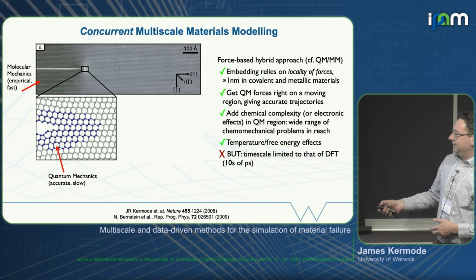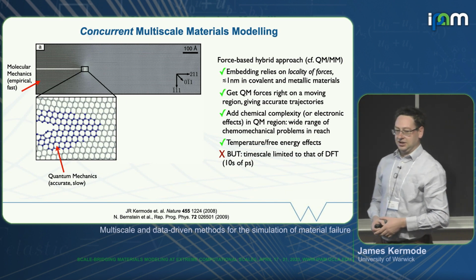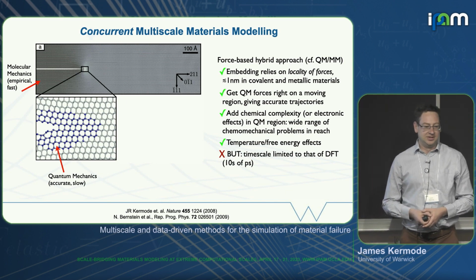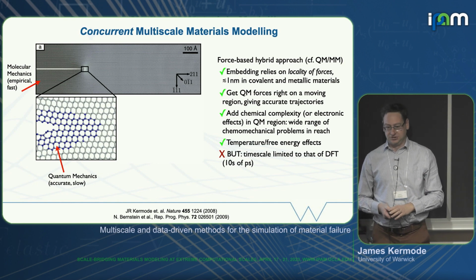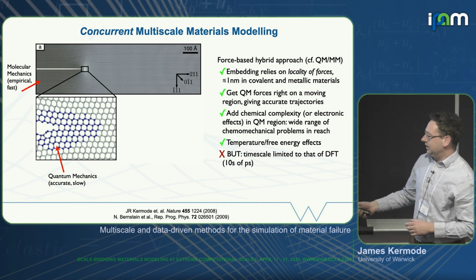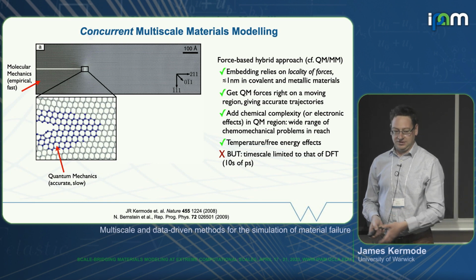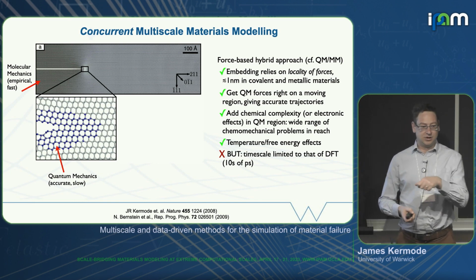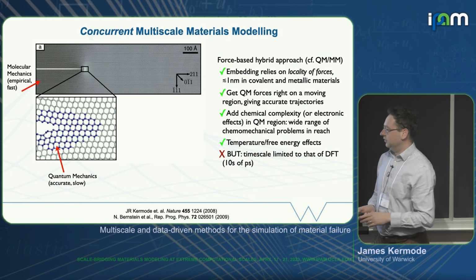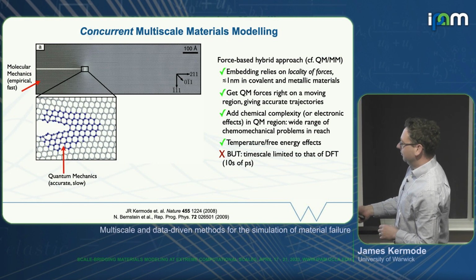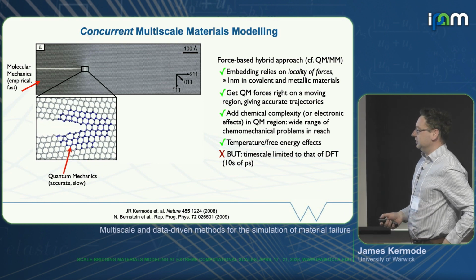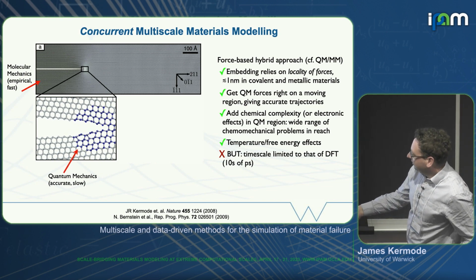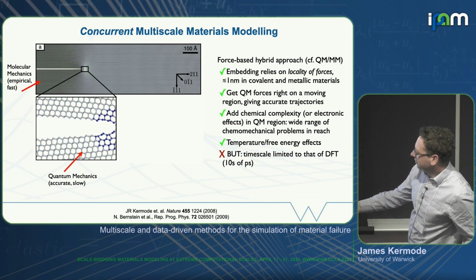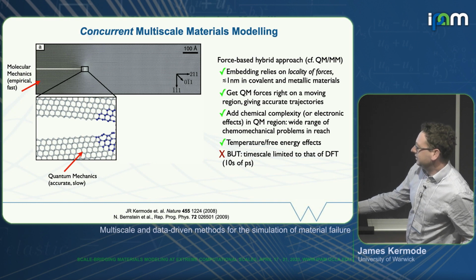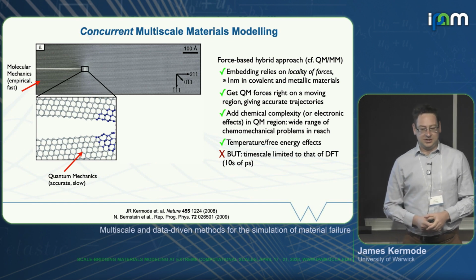That means that we can afford to have 10^5, 10^6 atoms described with a simple model. That's sufficient to capture the elastic relaxation and the long-range stress concentration. And then only where and when we need it, we can augment the description with a higher level method, in this case, density functional theory, which does correctly describe bond breaking in a wide range of materials. If we do that, then we recover the mirror smooth fracture surface behavior. We actually also see we get some quantum mechanical effects in the reconstruction of this surface. So you can see we have alternating pentagons and heptagons along that surface rather than just the pure hexagons that you get with the classical model.